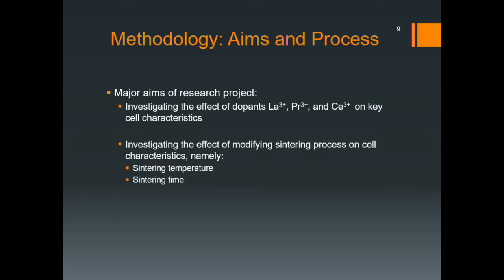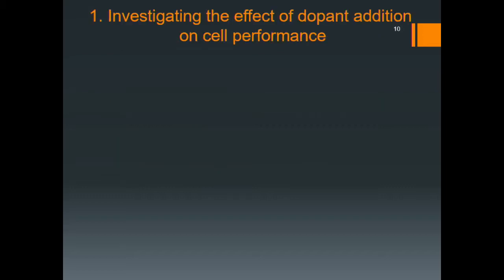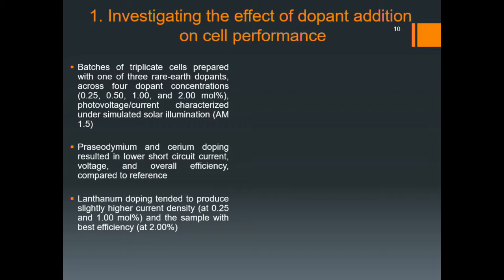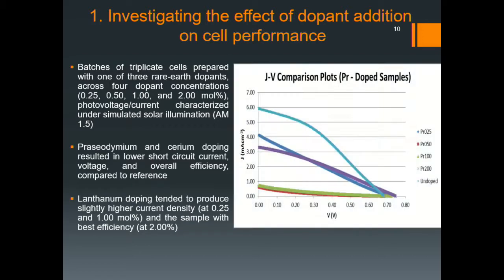This was based on advice from Dr. Farhat, my supervisor. So the first thing we did was to investigate the effect of the dopants. So we had these three dopants. We investigated the performance of cells prepared with these three dopants at four dopant levels, in addition to undoped cells. And these were characterized under fake sunlight, standardized sunlight, just to make sure that we had a reference, a stable baseline. So for our first dopant, praseodymium, this is an IV curve.